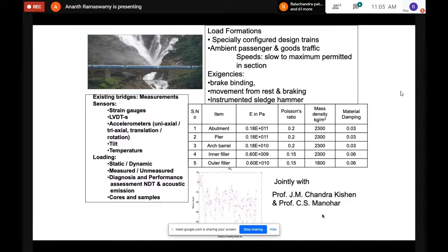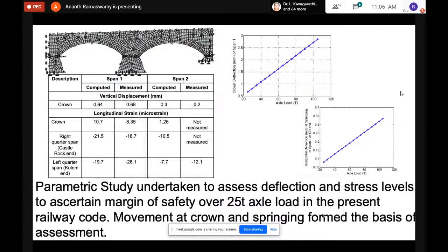And since this is a very old bridge, there are no drawings or design details. So we had to reconstruct our understanding of this bridge based on measurements and modeling, and try to reconcile these two to get a current condition assessment, and thereafter decide whether it can take a higher load. So in that context, we also did some finite element modeling and tried reconciling measured results with computed results. By suitably adjusting the material properties, the boundary conditions, etc., we were able to show how this system performed under the loads at which the field measurements were taken, and thereafter used the same model for enhanced loads to show that the system remained elastic in this revised domain.